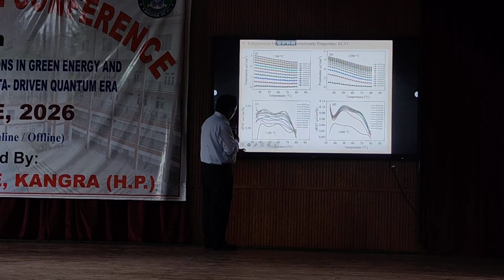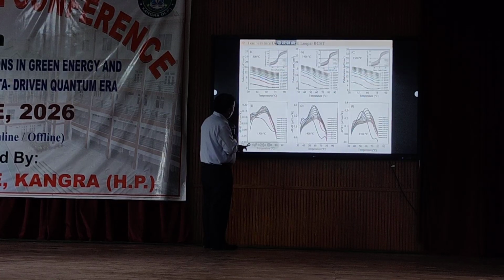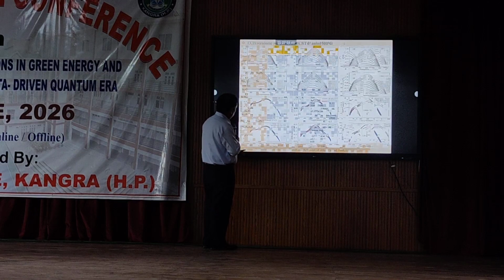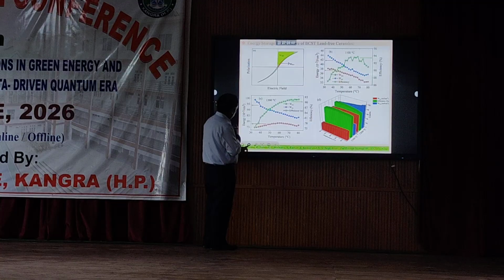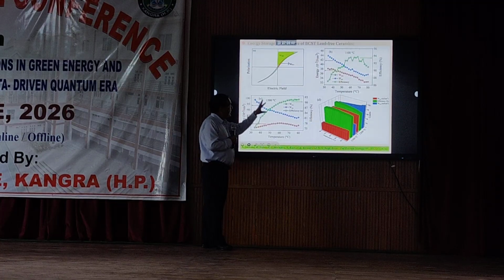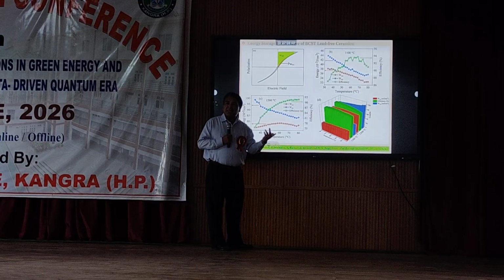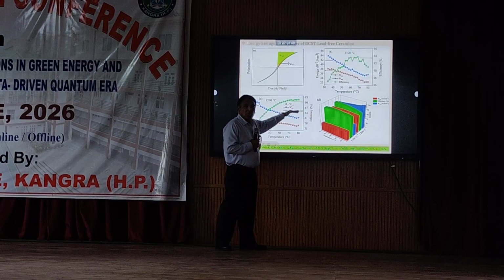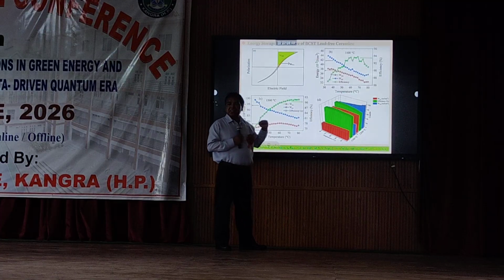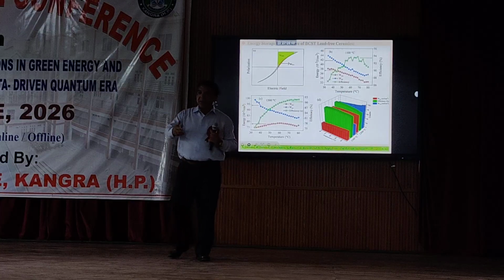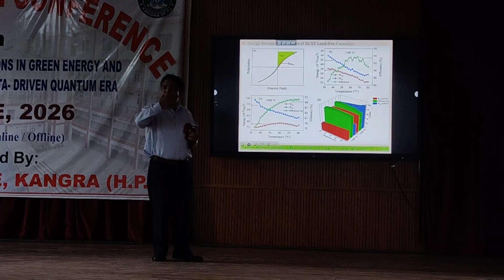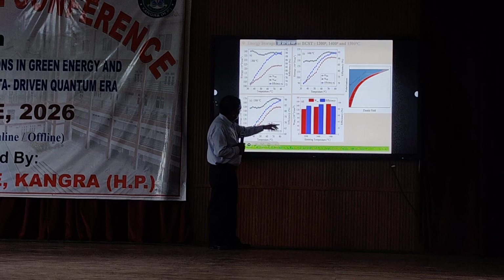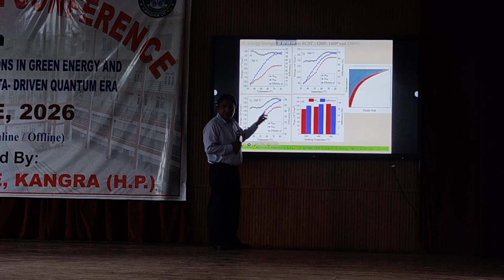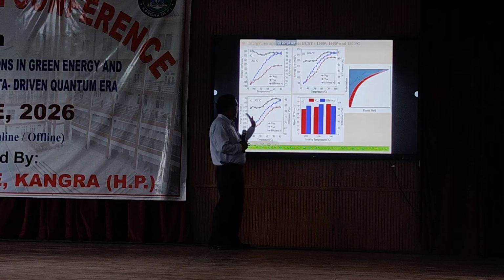And these are for evaluation of energy storage, similar to the earlier, but I want to show an important result in this particular slide. If you take this 1100 and 1200 degrees centigrade, again the same thing remains, that is high efficiency, low total energy density, low recoverable energy density. But when you create that morphotropic phase boundary, try to see that both things are slightly improved. So this efficiency, which is blue color, efficiency increasing, recoverable energy increasing, total energy also increasing.